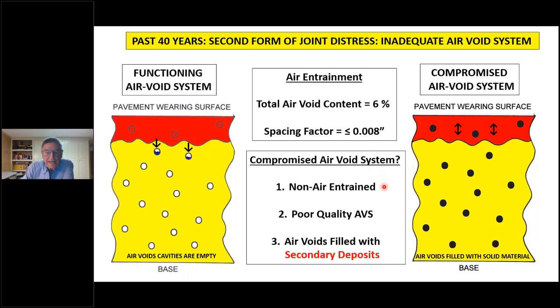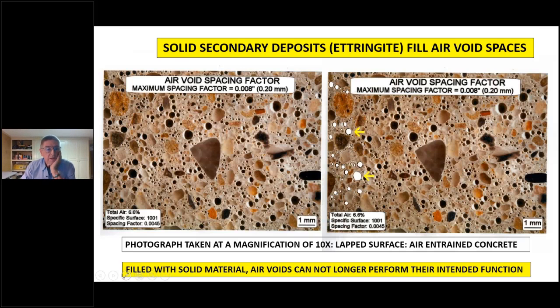We did not find any of our 20 pavements where the concrete was non-air entrained, and even in the case where the air void content was down, the spacing factors look good. So what we've seen in all 20 of these pavements in the joints was what I'm going to be describing here, where the air voids are filled with secondary deposits and lose their ability to perform their intended functions.